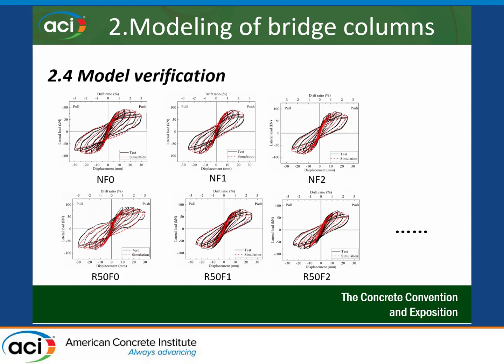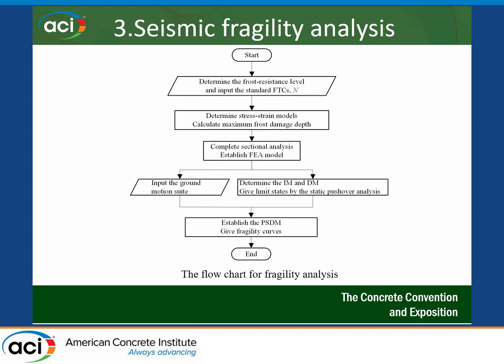The model was verified against experimental results of freeze-thaw cycles. A total of six specimens were tested and validated under lateral loading conditions to simulate the response of recycled aggregate bridge columns under freeze-thaw cycles. Once validated, fragility curves were developed using a suite of ground motions, establishing the relationship between intensity measure and damage parameter through a probabilistic seismic demand model.